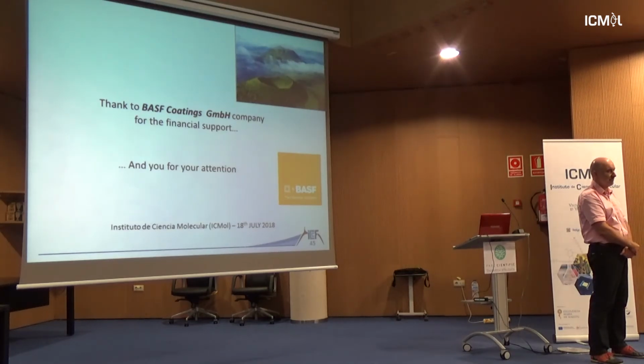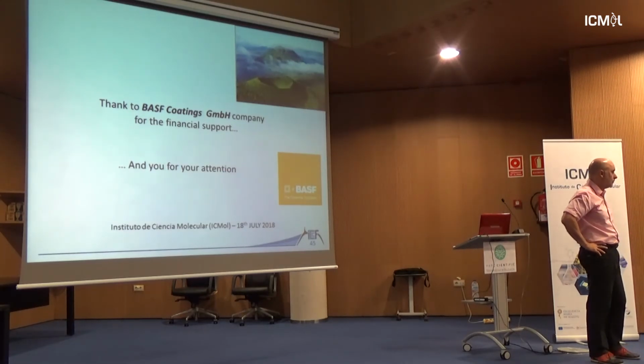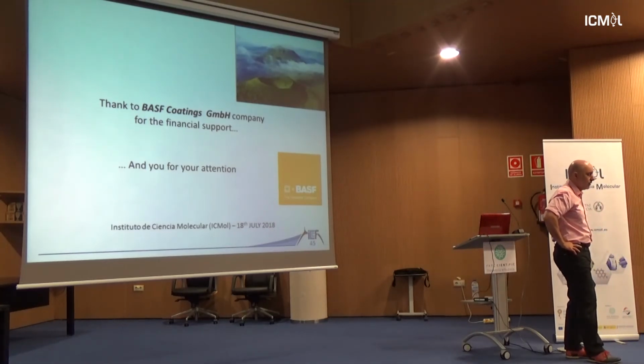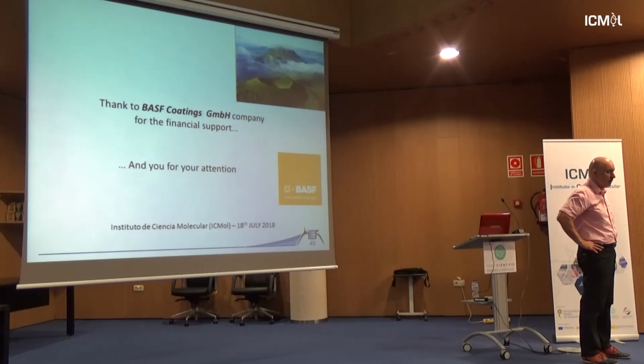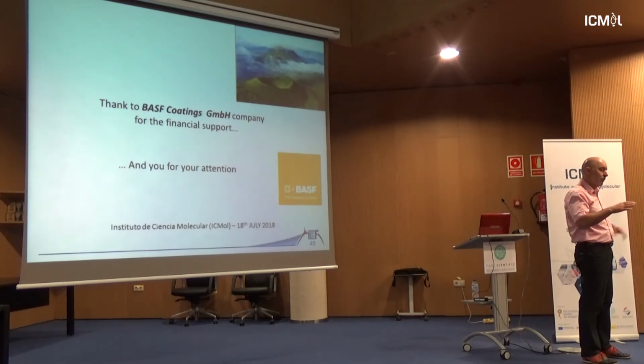Other questions? Maybe we'll ask the last one concerning the coatings. So you mentioned that you use white LDHs like magnesium aluminum or zinc aluminum, but in terms of pricing, these are also the best options, or? Yes, okay. Yes. Hydrotalcite, or even zinc. We use zinc mostly because it's more crystallized, so we can follow step by step what type of chemistry we are doing, because we can follow that by X-ray diffraction, so we can see the stacking and also the loss of stacking, and in fact, zinc and magnesium are completely reversible.